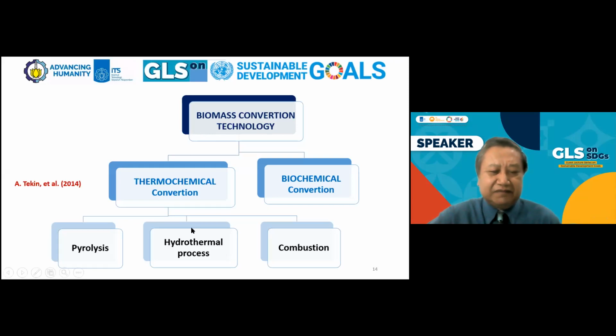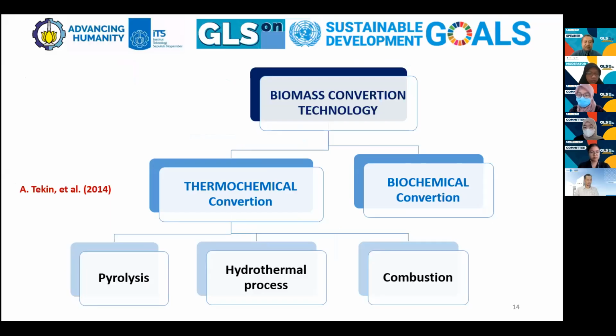The thermal method can be through a pyrolysis process, this one, which is heating in an inert gas atmosphere like nitrogen or argon. Next, the hydrothermal process requires water or liquid around a critical state at a temperature of several hundred Celsius at a certain pressure. In this process, subcritical or supercritical state can be selected. Lastly, the simplest process is combustion, like this.